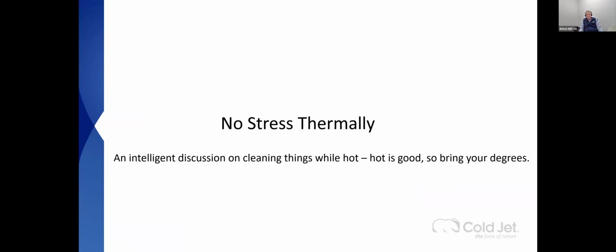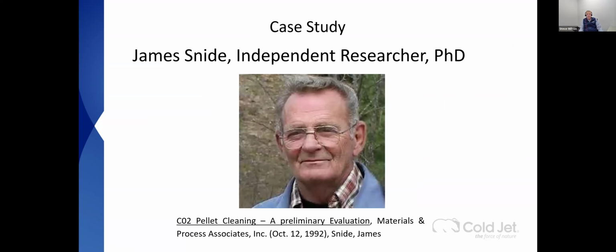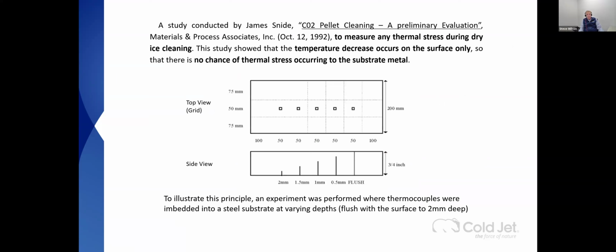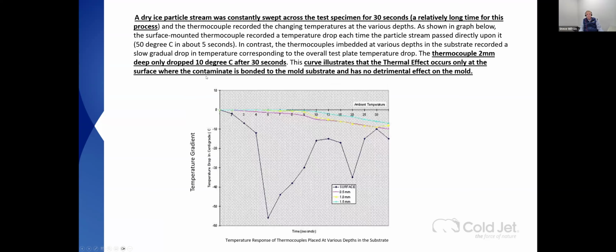No stress thermally. So bring the degrees of your mold. This comes from James Snide, an independent researcher. Once again, library material. You can jump right to the conclusions when he tried to measure thermal stress in dry ice cleaning. The temperature decrease across the surface only is one of the big reasons there's no chance of thermal stress occurring to the substrate. He blasted across this surface right here after putting thermocouples flush and at different depths all the way down to 2 millimeters. He swept across for 30 seconds, which for a piece that size is a pretty long time. The 2 millimeter depth thermocouple dropped 10 degrees after 30 seconds, illustrating the thermal effect only occurs at the surface of the mold, no detrimental effect on the mold.